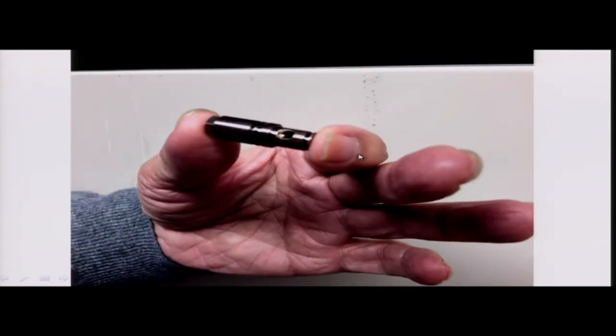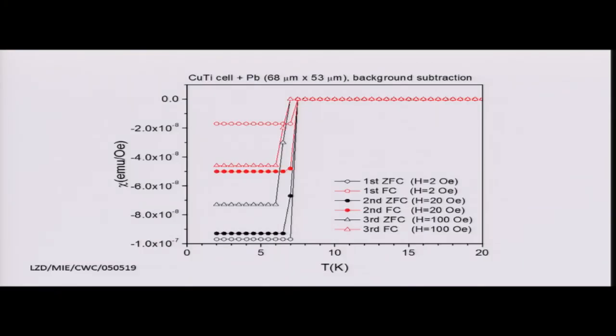The other thing is to try to see whether we can do magnetic measurements on this material under extremely high pressure. And this is the little cell that Eremets used to generate that high pressure. It's a little guy here, okay? That little cell over there, and the sample is locked inside here. So we try to see whether we can determine the magnetic transition in this material. What we have done first is put a piece of lead in there, of similar size to the sample, and see whether we can detect the signal, down to 10 to the minus 8 in our system. Indeed, we can see the transition, as you can see here.